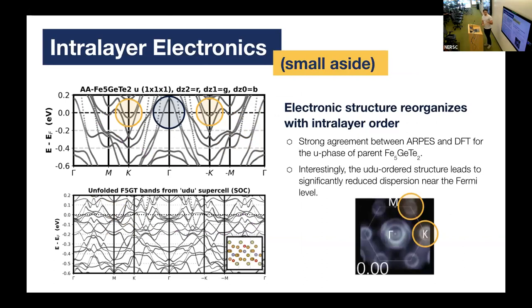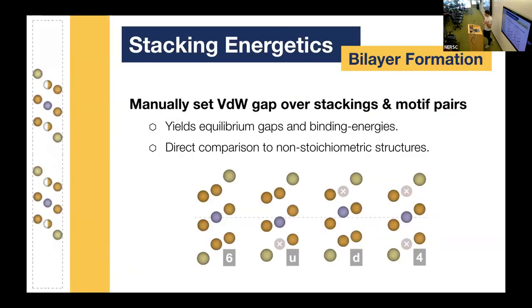This is a small side, so I'm going to go really quickly and maybe skip. But one of the things that's also very fascinating we're studying is the difference between that UDU phase and that UUU shows very dramatic changes also in the electronic structure. So the particular notes here is just that it is a metal, you can see by all the bands that cross through. But one of the things that's very interesting is that by going to the UDU phase, which is to say mixing up the Fe1 sites between different neighboring unit cells, suddenly you have a significant reduction in the dispersion. So we're actually working on trying to model this with some sort of tight binding model in order to explain exactly why suddenly at the specific K and gamma points within the unit cell, those get reduced by the ordering of these Fe1 sites. Back to the main part.